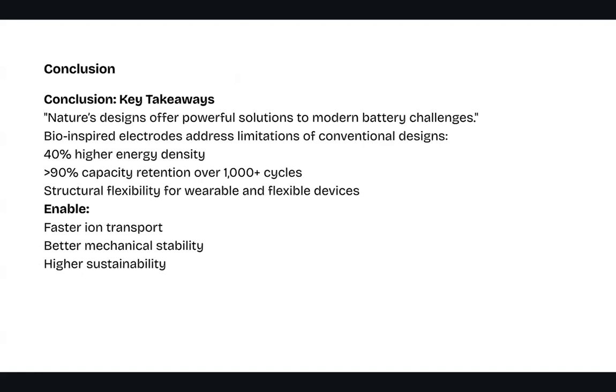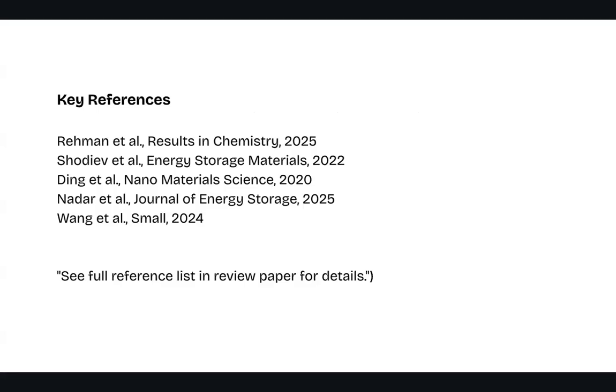So the overall conclusion of this bio-inspired electrode is that nature's design is a powerful solution to modern battery challenges. It helps to overcome the challenges we face from conventional batteries, and bio-inspired electrodes address limitations of conventional designs, such as 40% higher energy density, more than 90% capacity retention over 1,000-plus cycles, and structural flexibility for wearable and flexible devices. These bio-inspired electrodes enable faster ion transport and better mechanical stability, and also higher sustainability. So this is the overall conclusion of this bio-inspired electrode.